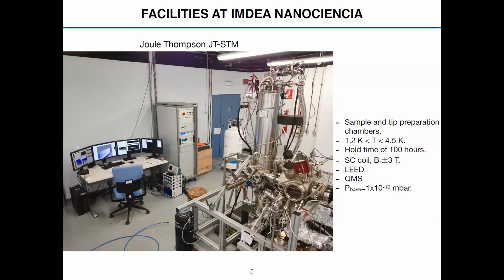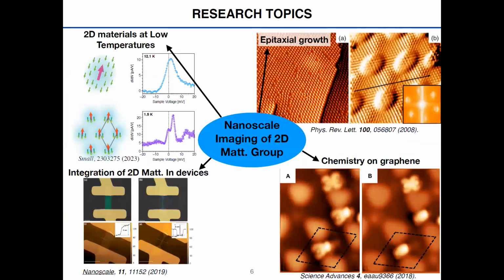It also has available a magnetic field produced by a superconducting coil, and this magnetic field is perpendicular to the plane of the sample. All of the STMs have other techniques like LEED, QMS, and work in high vacuum. These are some of the research topics of the group: epitaxial growth, chemistry on graphene, some integration of these 2D materials in devices, but this is done more in collaboration with other groups at the Institute of Nanoscience, and also research on 2D materials at low temperatures. I have more experience in epitaxial growth, chemistry on graphene, and these 2D materials at low temperature.